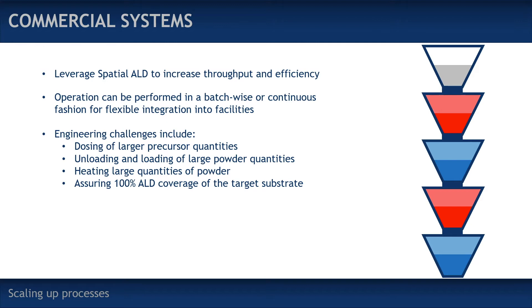The focus for lab systems was mostly on adaptability and ease of use. Now moving to commercial systems, the focus shifts more towards safety, cost efficiency, and throughput efficiency. When talking about commercial scaling, we're usually looking at spatial ALD. This is different from typical batch ALD, where you pump and purge precursor through a single chamber with the substrate remaining in place. With spatial ALD, the substrate actually moves through different precursor zones, removing vacuum purging from your throughput calculation and allowing more of a continuous processing mode.